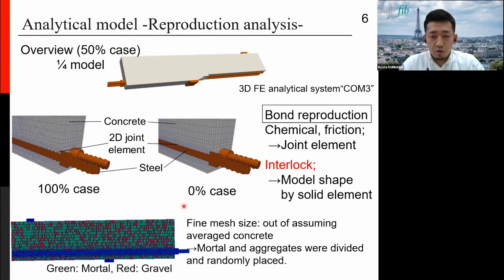In the original concrete model in this system, concrete components such as a cement matrix and aggregate are averaged as a concrete element. However, this model is not appropriate in this case because the mesh size is much finer. Therefore, in this model, the concrete part was divided into two types of elements, the mortar element and the gravel element, and randomly placed based on the volume ratio from the mixed proportion in the experiment.